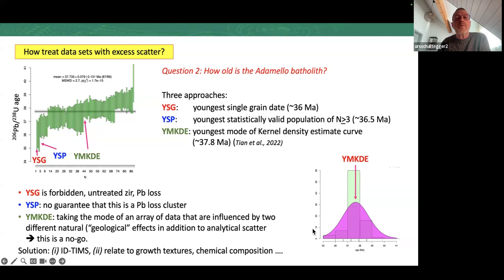Then what we could do is a kernel density estimate curve. We take the mode and we say, okay, the youngest mode of the kernel density estimate curve is giving our age. This would be around here. So what we do is mix together two natural phenomena, lead loss and memory of some older components, together with an analytical scatter, and call this then a best estimate for the age. So for me, personally speaking, this is an absolute no-go. We are not allowed to do this because we are mixing together sources of error of very different nature.